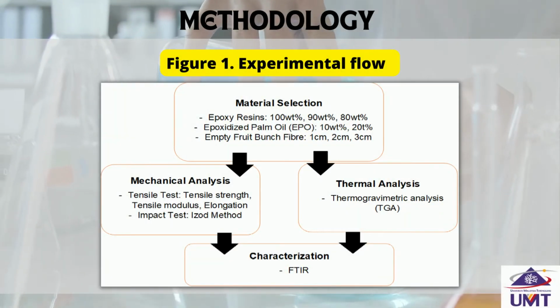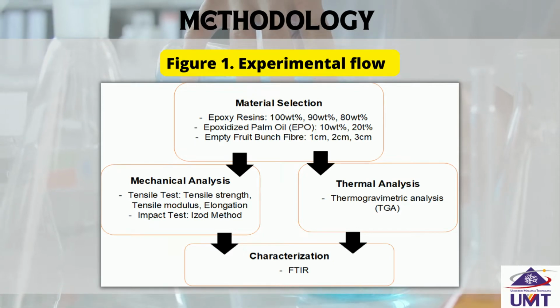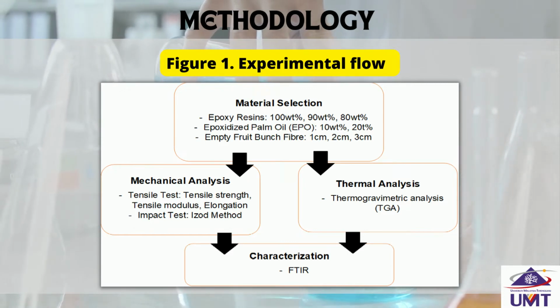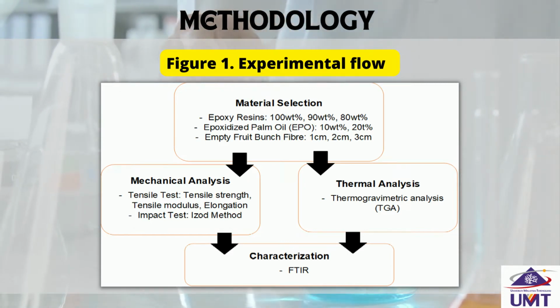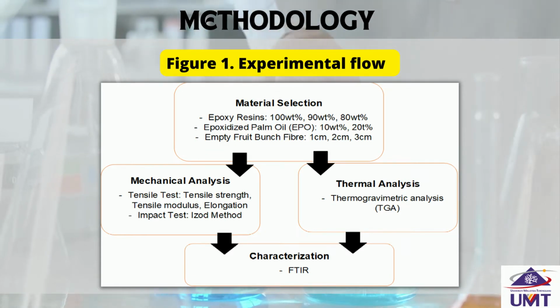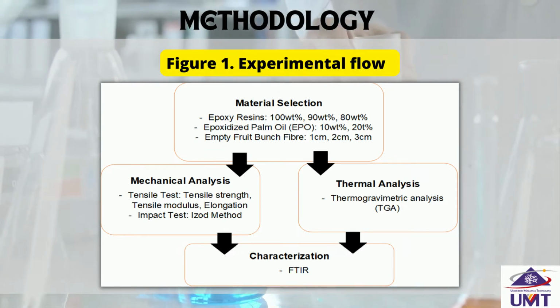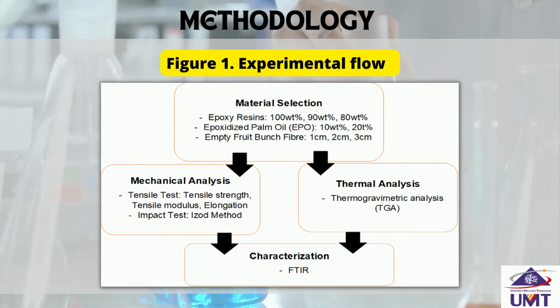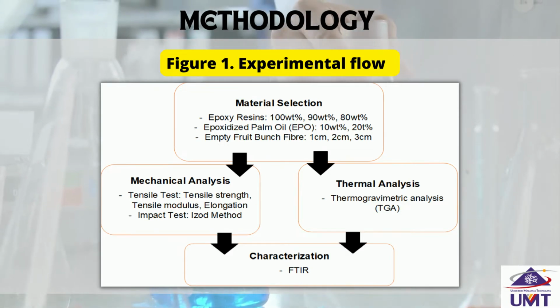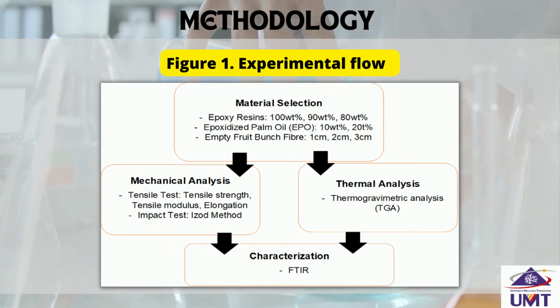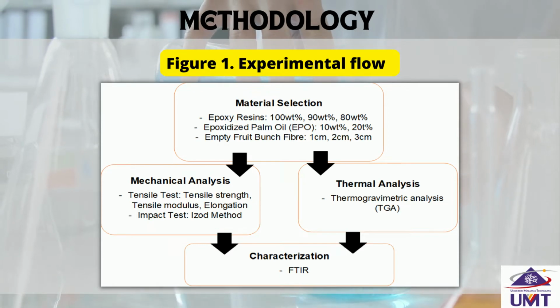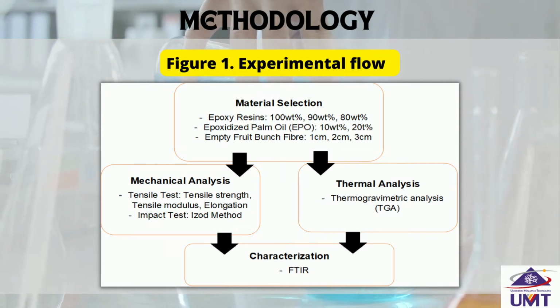In this study, the natural fiber, which is empty fruit bunch, with different sizes of 1 cm, 2 cm and 3 cm, will be used as reinforcement in epoxidized palm oil composites. The fiber will be treated with sodium hydroxide. Next, the mixture of epoxy and EPO will be added with hardener. Then the treated fiber will be mixed together with the epoxy EPO composites and laid on the open mold. Lastly, the curing process will be done by pre-curing at 80 degrees Celsius for 2 hours and post-curing at 110 degrees Celsius for another 2 hours in the oven.